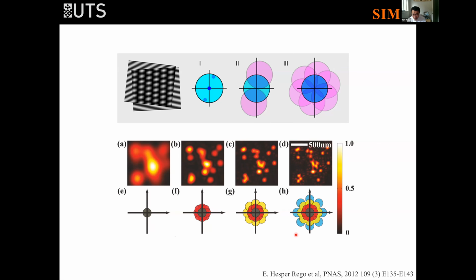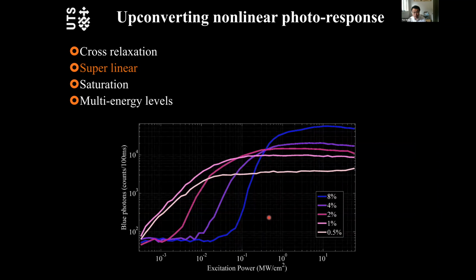So the only challenge is, if you want to trigger this nonlinear effect, usually you need to use really high power. And for SIM, because it's a wide field super resolution technology, it's really hard to use really high power and trigger all these kinds of nonlinear effects. This is the reason why we want to use our nanoparticle, because for our nanoparticle, you just need to use a tiny bit of power. Actually, you can have a really good nonlinear effect here.